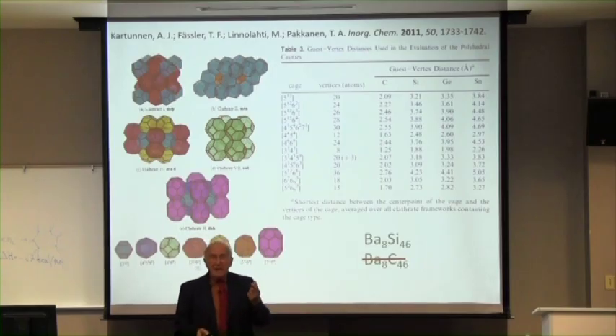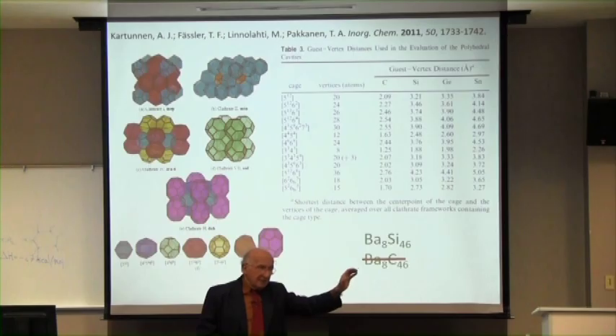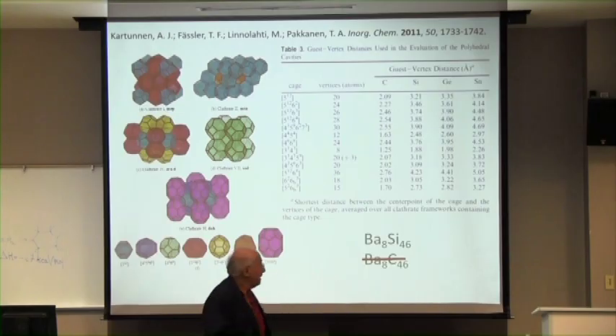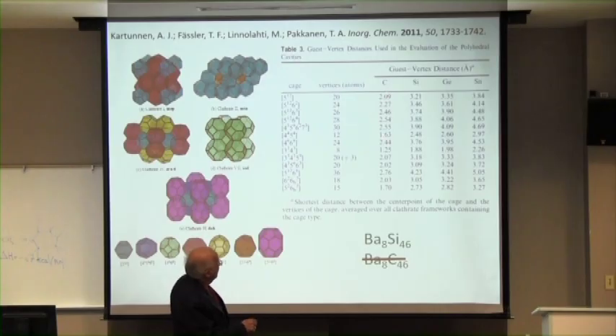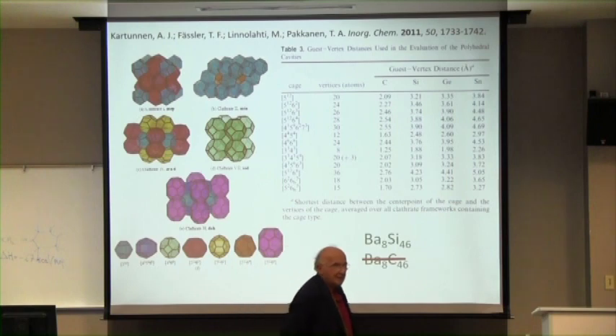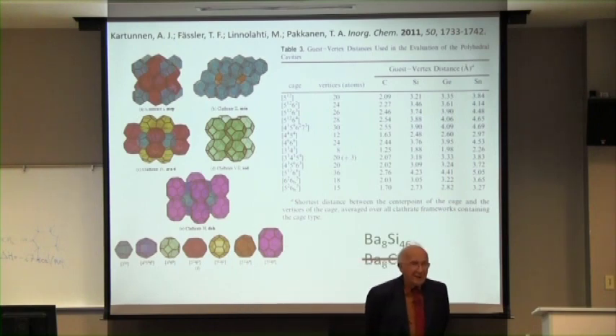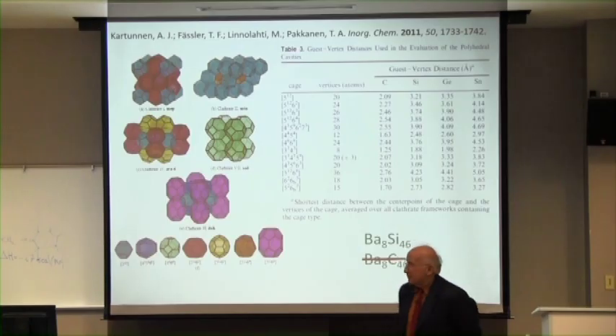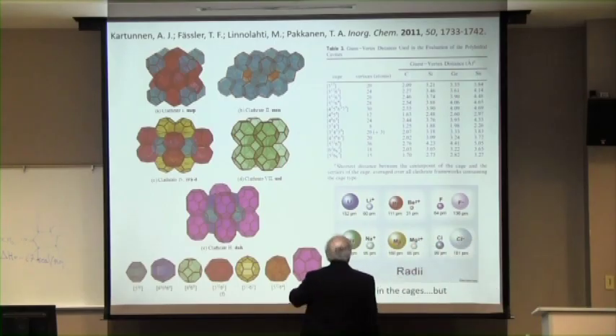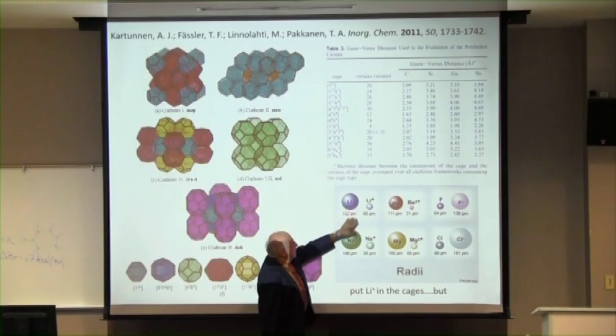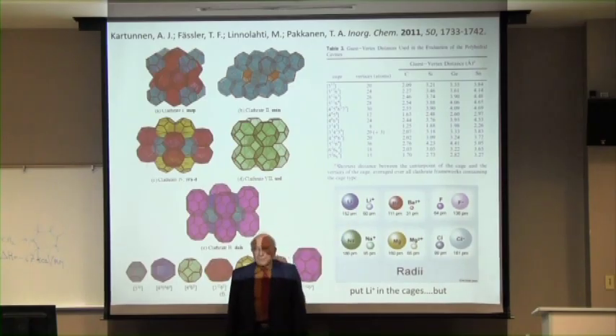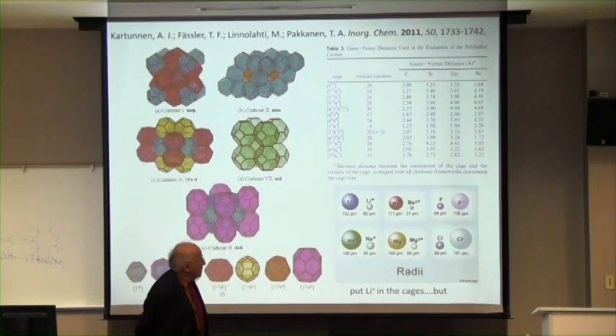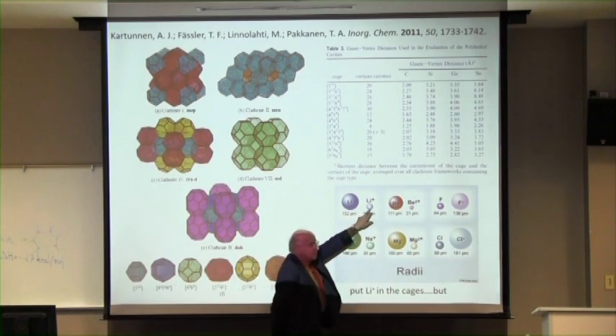So here's the difference. The block outside, the clathrate, is made out of all single bonds. That single bonds are 2.35 for silicon, but are 1.54 for carbon. And the size inside the box for carbon is around 2 angstroms inside the dodecahedron. And that is not good news. That's too little for even the smallest atom. A helium even has trouble, but helium might just fit in, but helium is not interesting in this chemical context. Lithium and beryllium are too large to fit into that cage. But we thought maybe we could put in lithium plus.